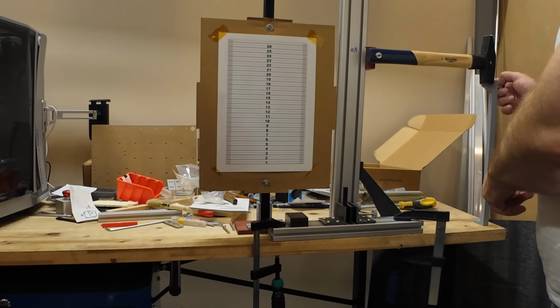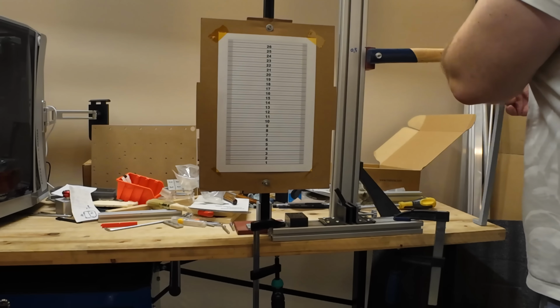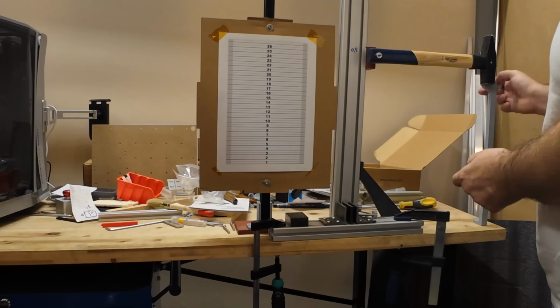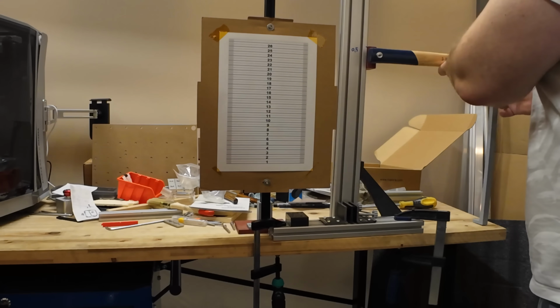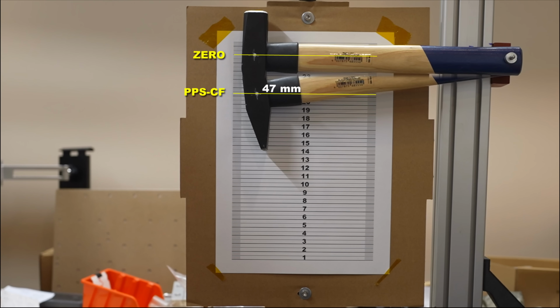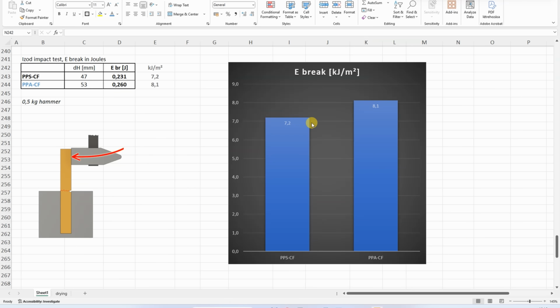Impact test with this 0.5 kilogram hammer. Zero position. Distance from the zero position is 47 mm, and from this I can calculate the breaking energy. Both materials are very similar in this test. They are more brittle compared to the average ABS, but still tougher compared to the average PLA.